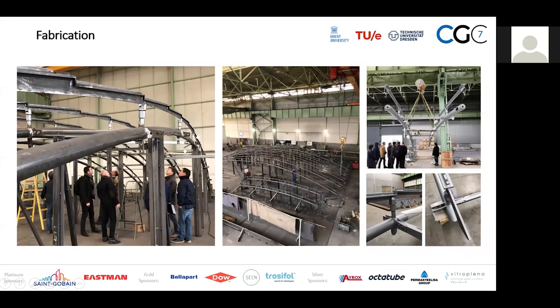Just to give you an impression of the fabrication and pre-assembly of the structure, the entire structure was constructed and designed with zero tolerance, not a single millimeter of tolerance anywhere. So it had to fit perfectly. It was checked with templates in the factory here. On the right-hand side, you see these prefabricated steel ladder frames. This is basically what was shipped from Europe to the United States, to Los Angeles.